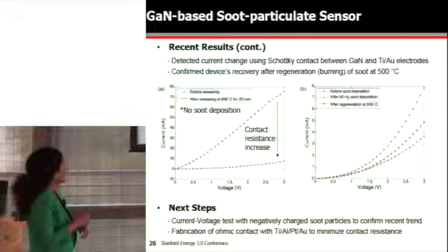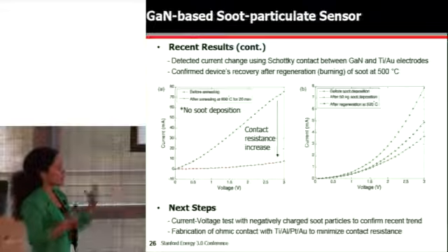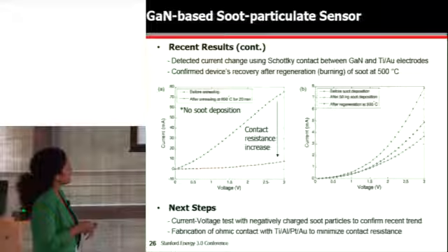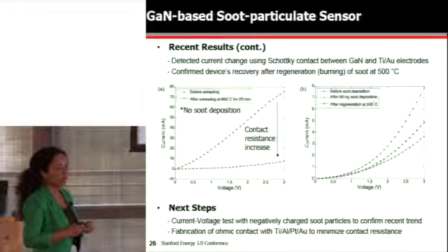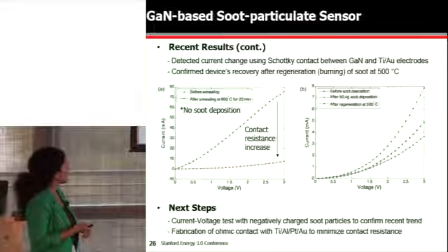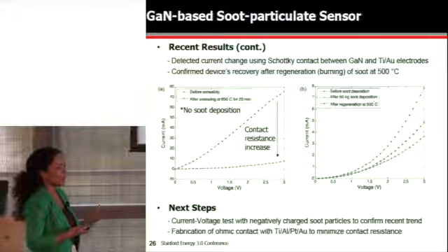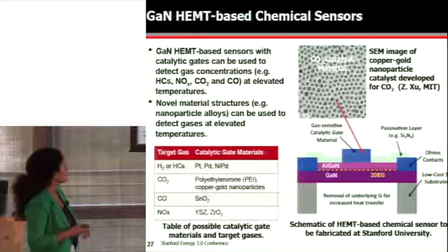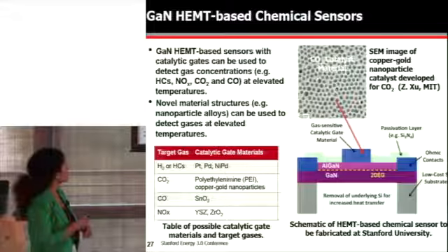So we do a burn-in process where the contact resistance increases. And then before soot deposition, we can see the IV response. And then after deposition of soot, we can see the red curve here. There's a change in the IV response. And then after regeneration, or heating and burning off the soot, we can see recovery of the response. And so we can use these gallium nitride sensors to create high temperature soot particulate sensors.